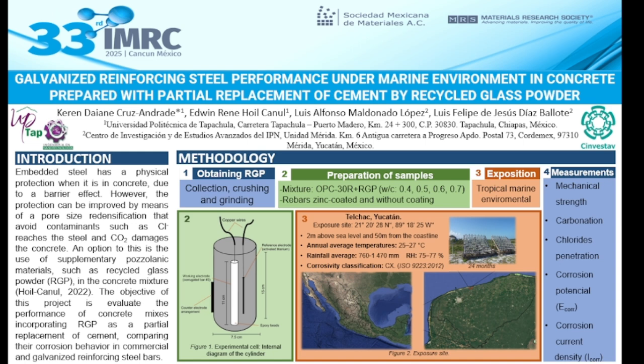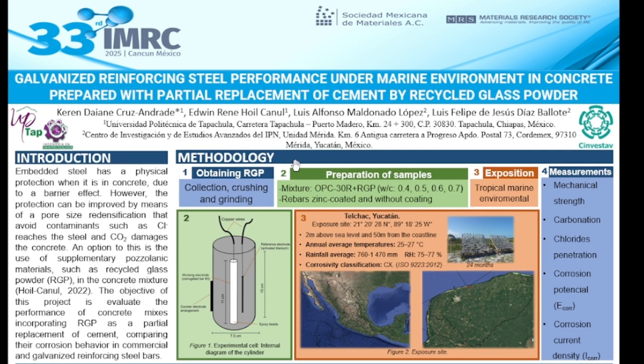mixture. The objective of this project is to evaluate the performance of concrete mixes incorporating RGP as a partial replacement of cement, comparing the corrosion behavior in commercial and galvanized reinforcing steel rebars. The methodology of the work is divided in 4 steps. In the first step, we obtain RGP. We start with collection, crushing, and grading, and grind to an average particle size of 30 micrometers.